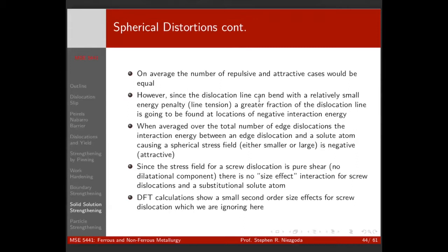alloy, right, the alloying atoms are fairly well separated, long compared to the Burgers vector. So what happens is the dislocation tends to want to stay near the attractive regions. You'll have to give extra force to move that part of the dislocation away from where it's attracted to. And it will stay away from the repulsive regions, the positive energy regions. And you'll have to give it extra energy to push it past those regions. Right? So you get strengthening effects from both above the slip plane and below the slip plane, and positive, bigger and smaller, simply because the dislocation line can move, can bend, and your dislocation wants to be in those low energy configurations. And you have to give it extra force to move it out of those low energy configurations into the high energy configurations. Right?